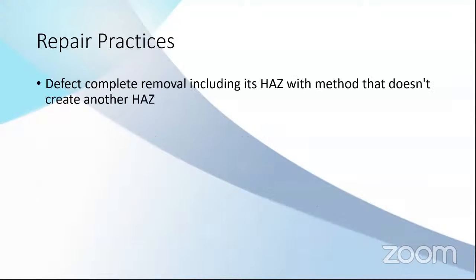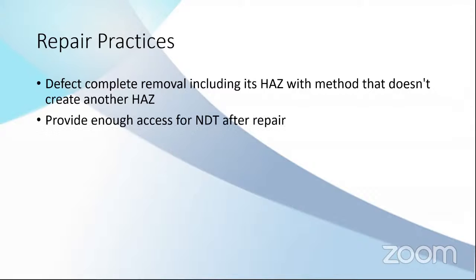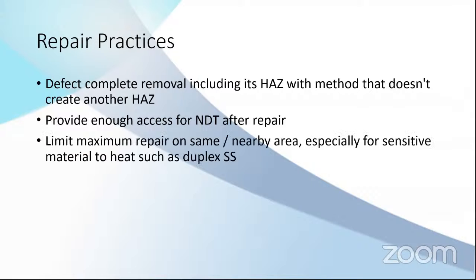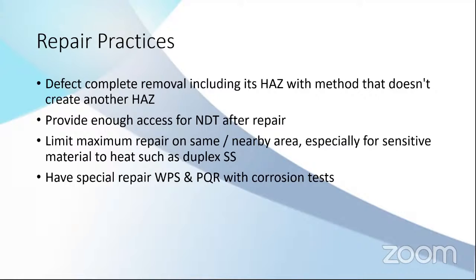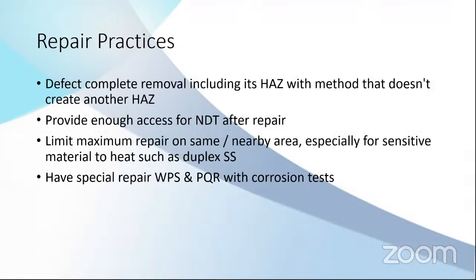For repair, this is the common specification. If you have defect removal, try to remove it completely with the HAZ. Provide enough access after repair, so you can inspect it again, and limit the repair if possible. If it's duplex, probably you cannot repair it. You need to cut and re-weld again, and have a special repair welding specification and PQR, including the corrosion test, just to make sure that the repair process will still have good corrosion resistance to the material.